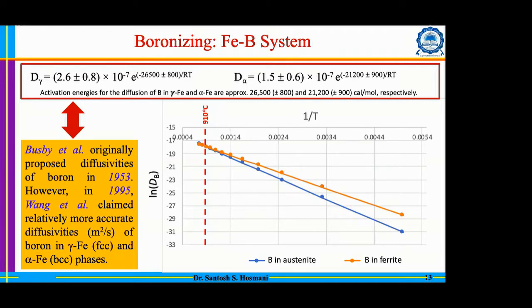Otherwise, from the phase point of view and solubility point of view, we don't have much requirement that we should be in the austenitic phase region or something. So people have successfully boronized even at 800 degrees Celsius. Also, they have boronized even pure iron. They have successfully boronized. So that is what we have.